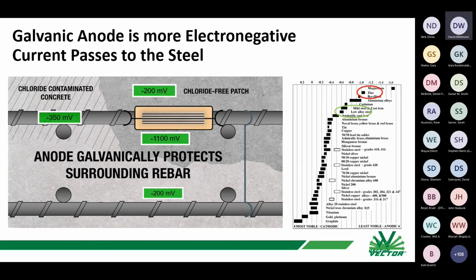You'll see a few of these when we do the walkthrough. Illustrated in the graphic is a galvanic anode, and you'll see some galvanic anodes like this when you go out to the job site. That anode's electrically connected to the steel inside the repair area. The closer it is to the edge of the repair, the more effective it is. And this works because inside the anode is zinc. Zinc is more electronegative than steel.